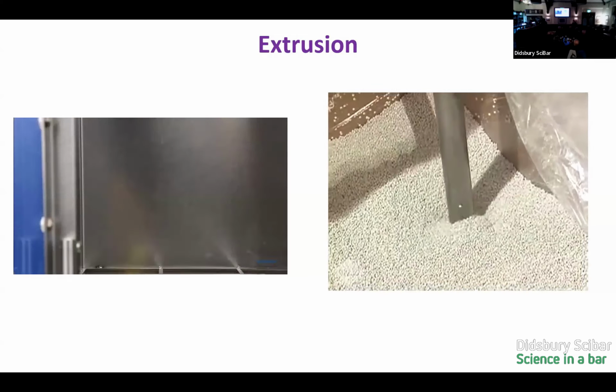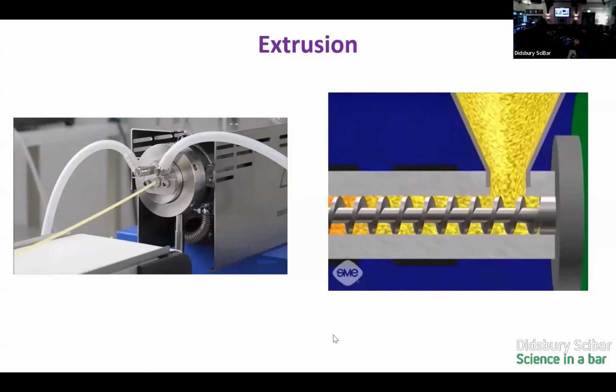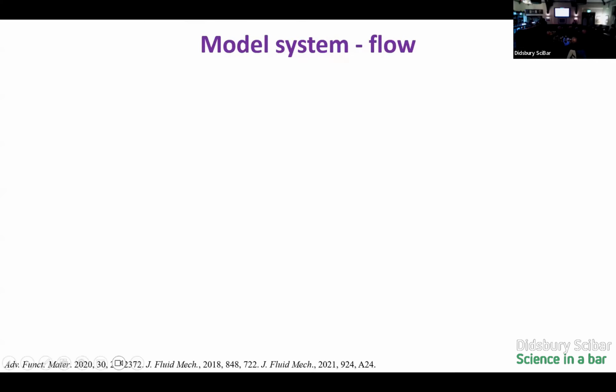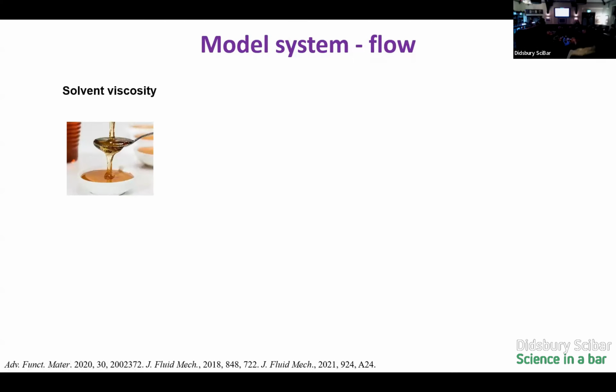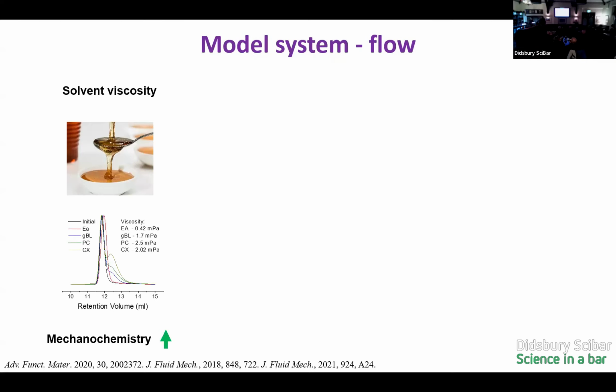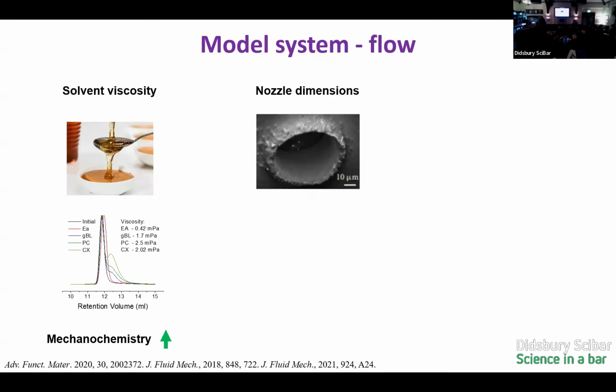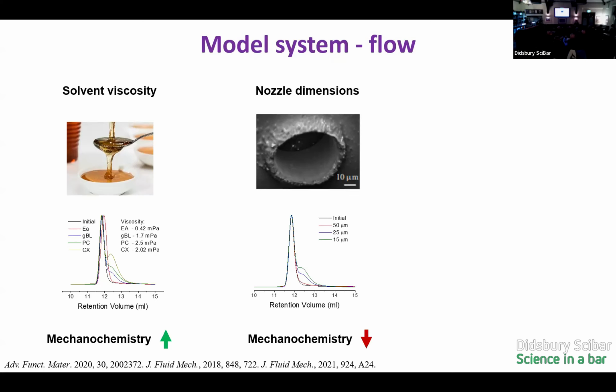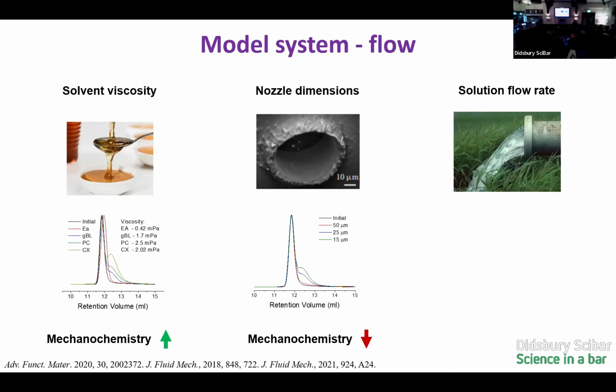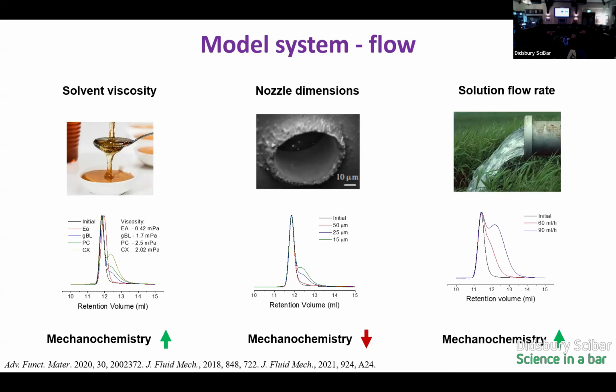So then how does our mechanochemistry in sonication compare to extrusion? And that's what we've been looking at over the last while. And we found that there's a number of things that are also important that aren't so important when you look at sonication. So viscosity is really important. As we increase the viscosity, we increase the amount of mechanochemistry we get. As we decrease the nozzle diameter, so as we decrease the size of the nozzle that material has to go through, we increase the amount of mechanochemistry that we get. That arrow is pointing the wrong way, or I've said that the wrong way around. As the nozzle gets smaller, we get more mechanochemistry. And then as we increase the flow rate, we get an increase in mechanochemistry. So essentially, as we push it through the hole faster, we can stretch out our polymer chains faster and get more mechanochemistry.